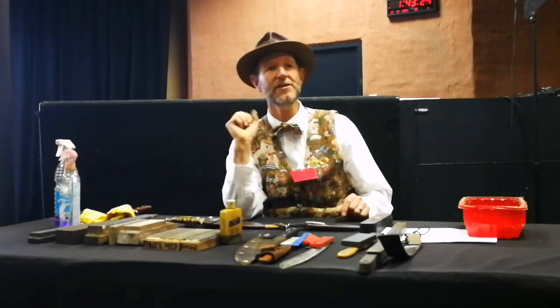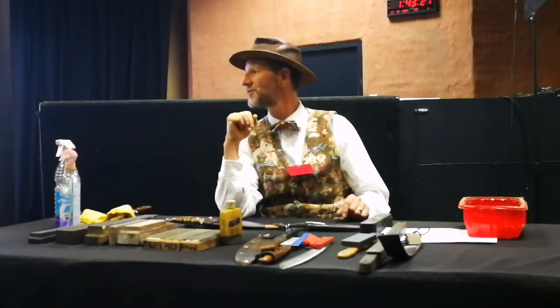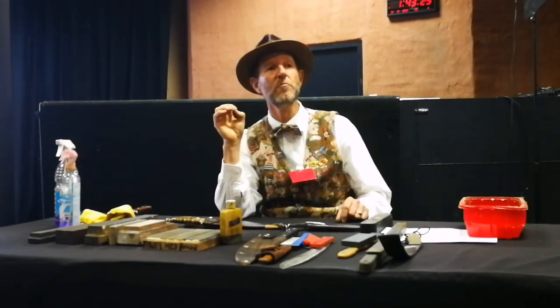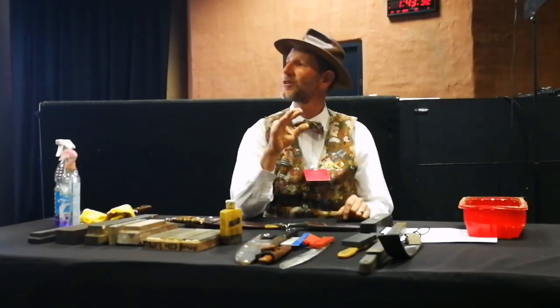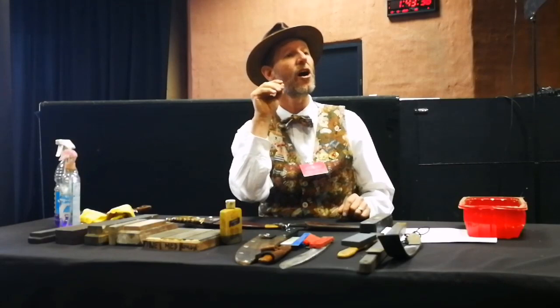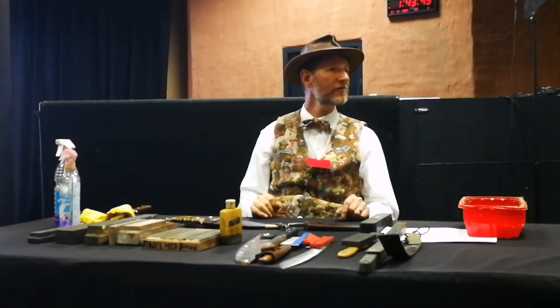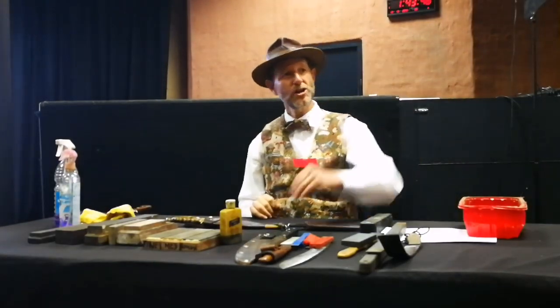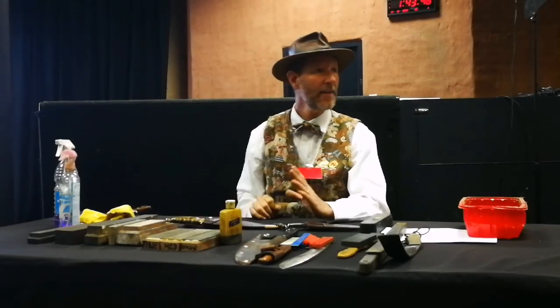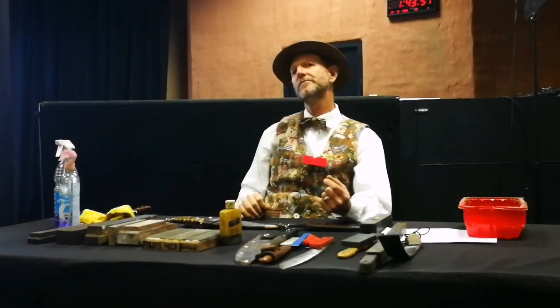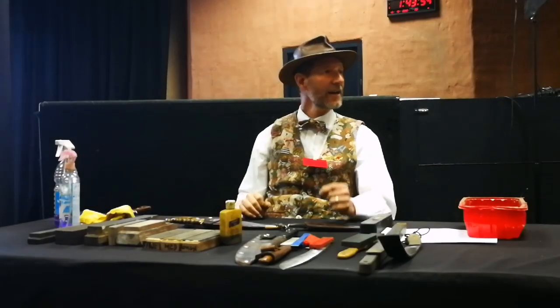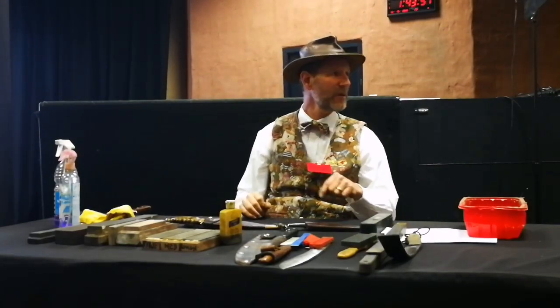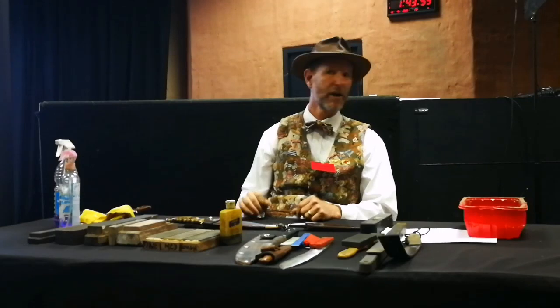And after hardening, it went into the tempering oven at 180 degrees or 200 degrees, whatever the case might be, to reduce the brittleness and induce toughness and flexibility. The temperature at which you temper it after hardening results in the final hardness of your knife. You harden a knife by quenching it in oil, mostly. There are other exceptions. But the knife will come out of that quench as hard as it can be according to its carbon content, mostly.